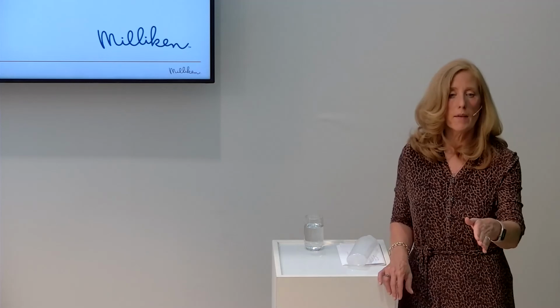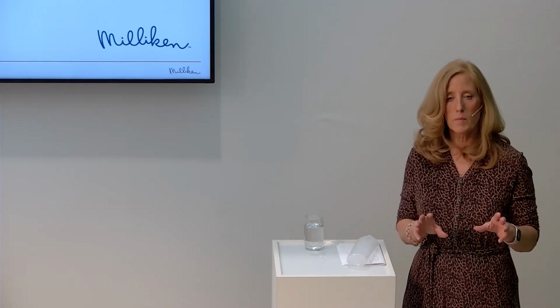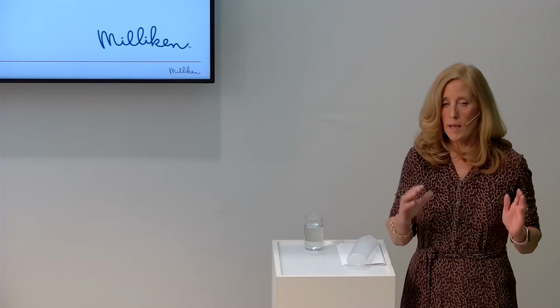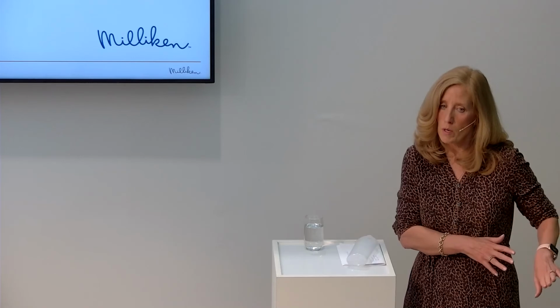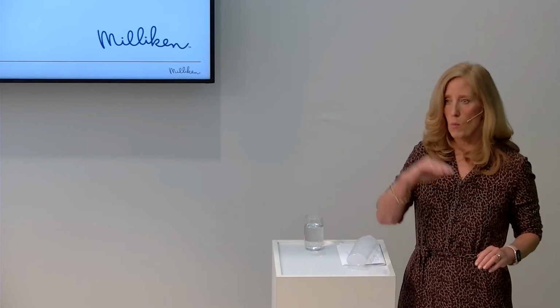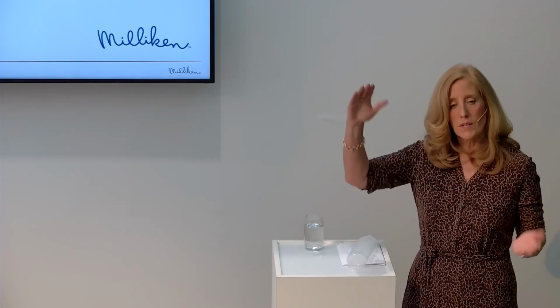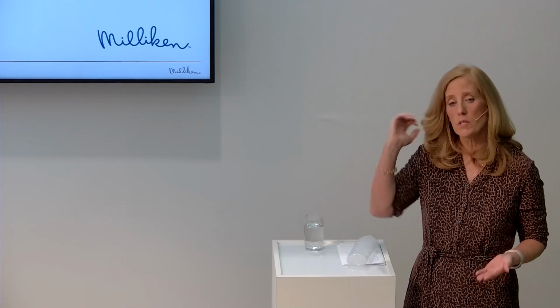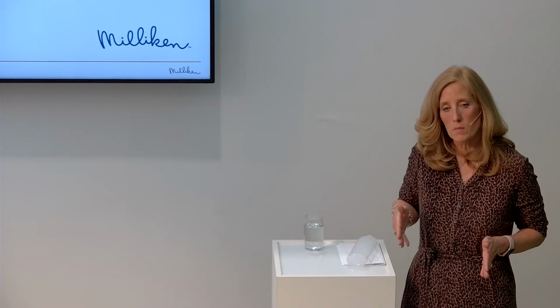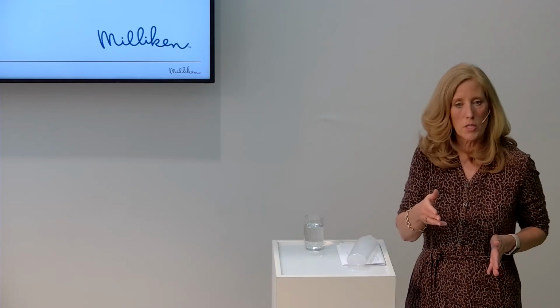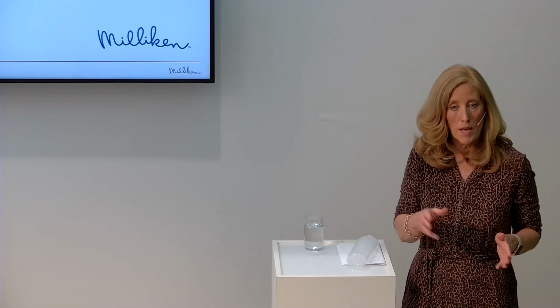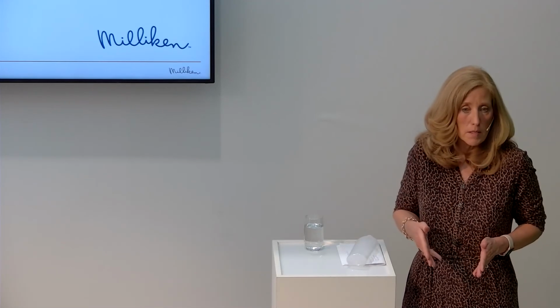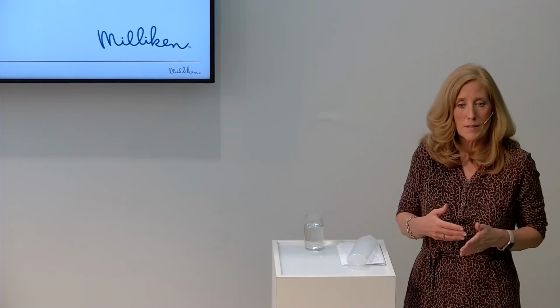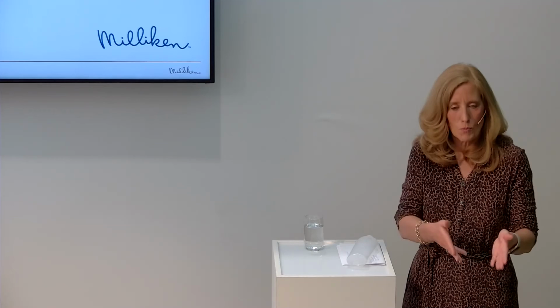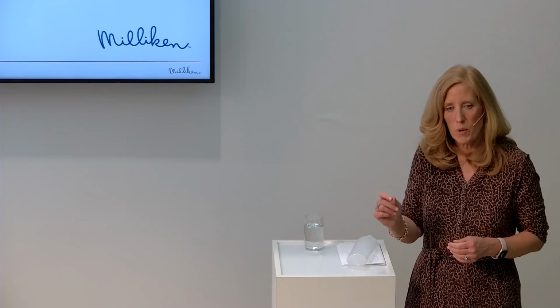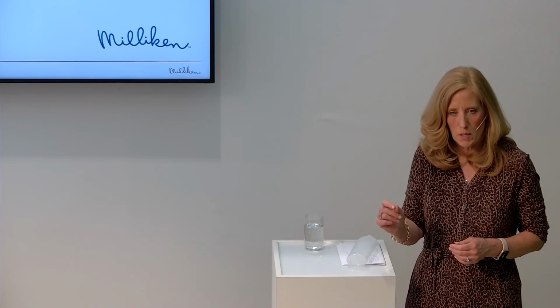I would say that dissolving can have its limitations, we think, if we went way lower than, let's say, a 5 melt or way higher than a 50 melt, because of the design of the temperatures and the pressure that we have in our dissolution system. A process engineer would need to be ready for a big change and adjust that. We can still dissolve it, but it's going to be more or less viscous without making some process engineering changes.